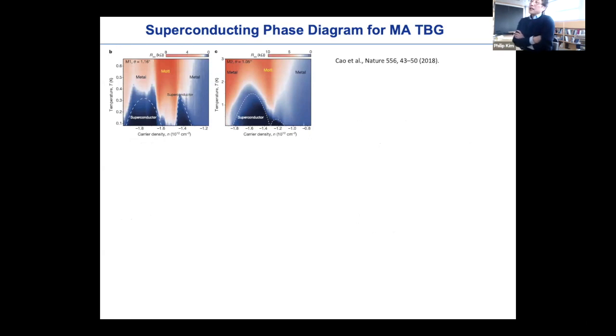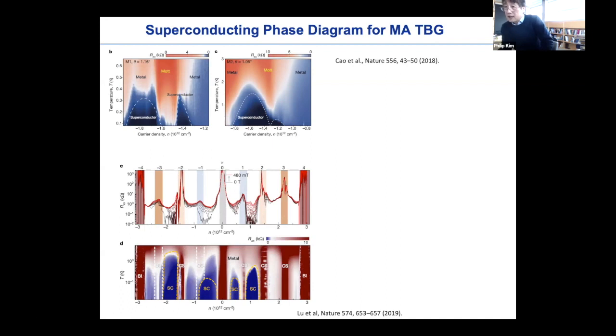So I will start with this phase diagram, which has already played an important role a couple of times, right? This is the very first phase diagram, of density versus temperature, of magic angle twisted bilayer graphene done by the MIT group. Here the twisting angle is 1.16 and 1.05. There are quantitative differences, but qualitatively they are similar. Basically, it seems like the insulator is dividing the superconducting dome. There seems to be some sort of competition between the correlated insulating phase and the superconductivity in the system.